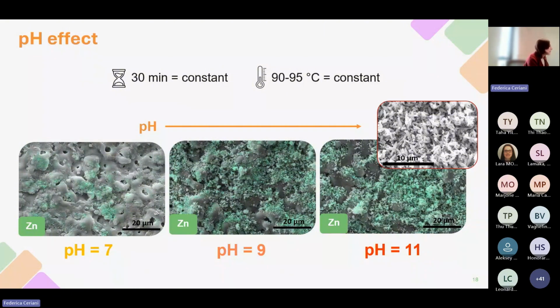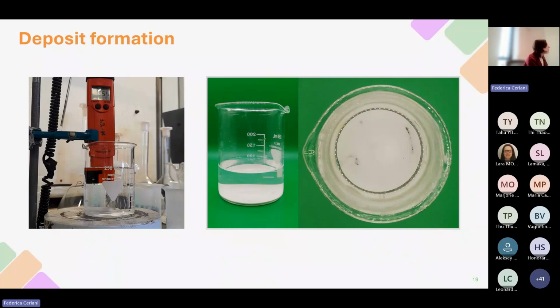So, it is observed that for increasing pH of the sealing bath, keeping constant all the other working variables, more numerous and larger precipitates are obtained, favoring a more enhanced sealing effect and then an increase in the corrosion resistance of the sealed coating. Moreover, in case of the most alkaline solution, the zinc precipitates that are produced are characterized by flower-like shapes.